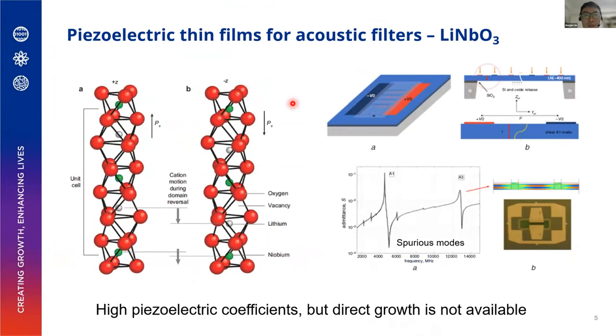And the second type of material, as we were talking about just now, is lithium niobate. So lithium niobate has this quite interesting hexagonal lattice where you have niobium sitting at the center of this oxygen octahedra. Then the next octahedra has lithium in the center. Then the third octahedra actually has no atom. So it's empty, there's no atom in the center. Then you repeat with niobium, lithium, empty. So it's kind of a spatial structure.